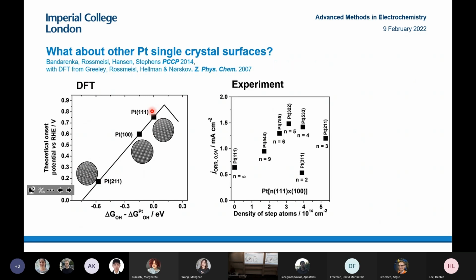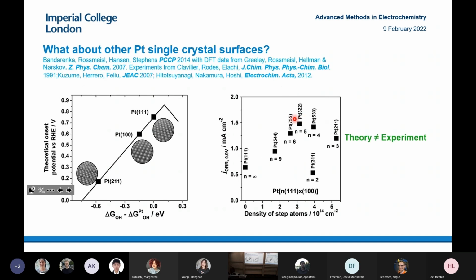However, if you look at the work of the group of Juan Feliu from Alicante, and also Hoshi from Japan, they've been looking at platinum single crystals, and what they found is that when you increase the step density, they actually see a modest improvement in activity relative to platinum 111. So it seems like the theory was completely wrong. So we had a closer look at their data.